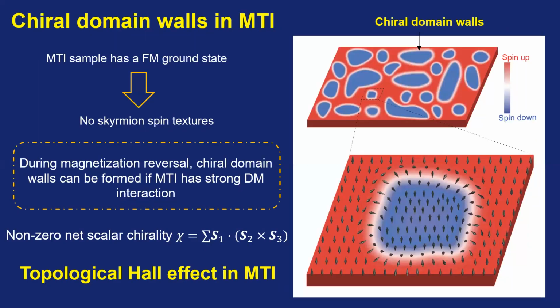And we want to explain why we can observe this kind of crossover between the topological Hall effect and the quantum anomalous Hall effect in this kind of magnetic TI sample structure. We know that in magnetic TI, the ground state is ferromagnetic, so there should be no stable spin texture. But we observed in our sample this hump feature around the QAH regime. So we suspect maybe there is some chiral domain wall in this sample, and this kind of chiral domain wall can form the chirality in this sample.